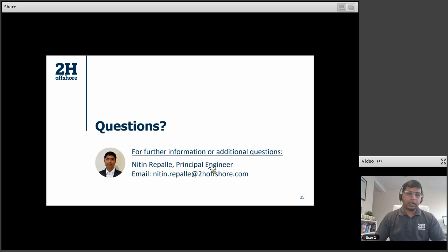Yeah, that's a good question. And I believe there's no straight answer. Like how we currently do for a traditional flexible pipe, we still need to qualify the pipe structure for erosion. And the good thing is, we have a lot of variations of the pipe. So if we see at a point where your polymer is eroding faster and it's not qualified, we still have a variation like what Baker Hughes is proposing, where you can still have your carcass within the composite hybrid flexible pipe, and which can provide the same level of strength against erosion that you would get for a traditional flexible pipe.